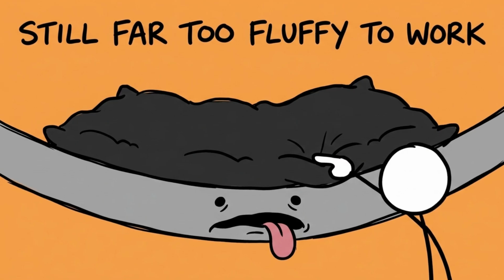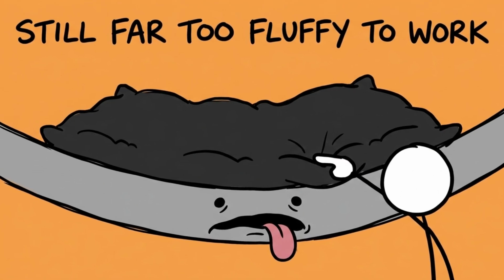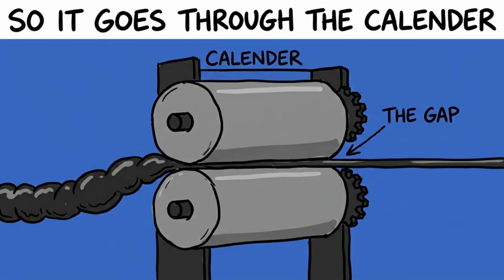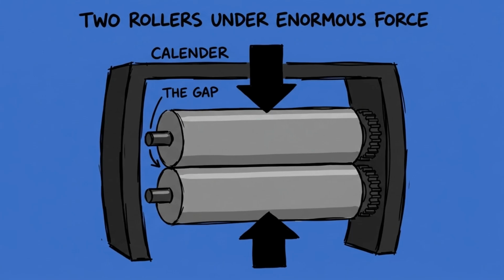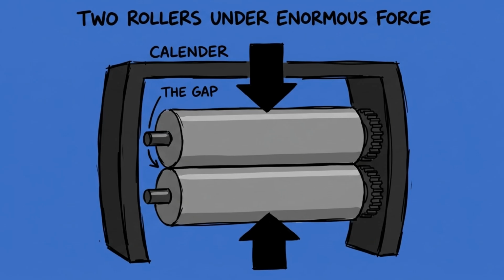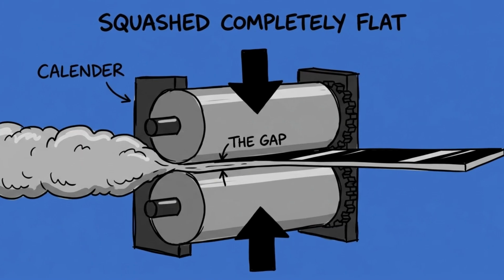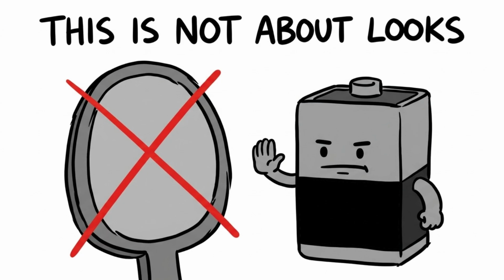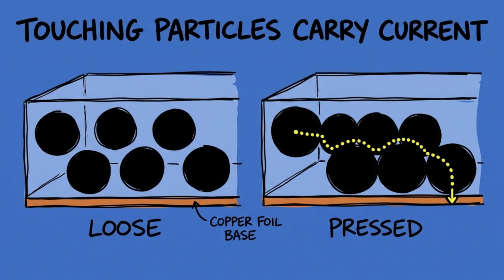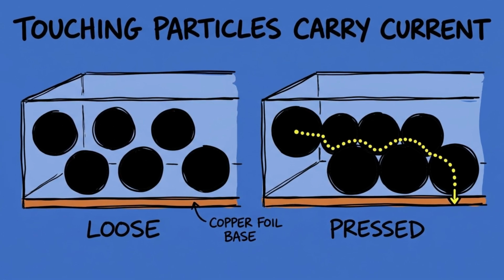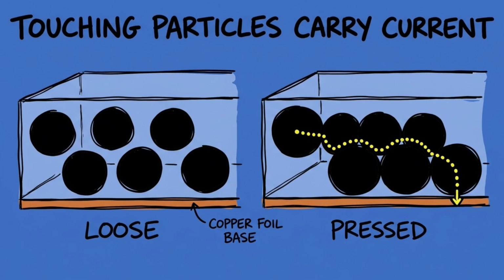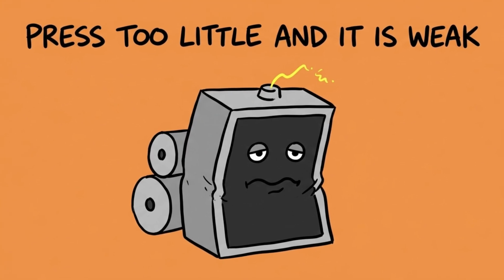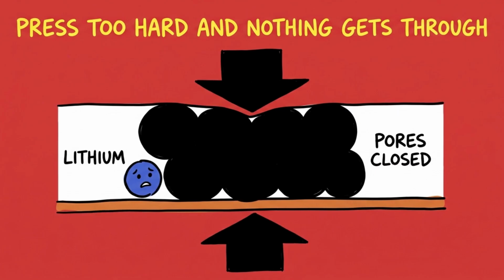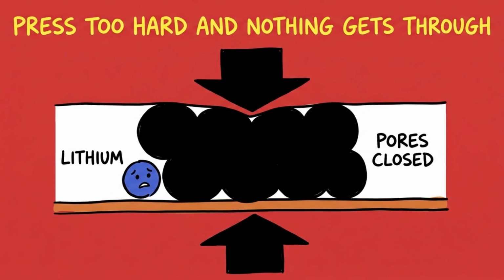What comes out the far end is coated, and it is still too fluffy to work. So it goes through the calender. 2 hardened steel rollers pressed together with enormous force, squashing the coating flat. This is not cosmetic. Pushing the particles into contact is what lets current move through the layer at all. Press too little, and the cell is weak. Press too hard, and you crush the pores the lithium has to travel through.